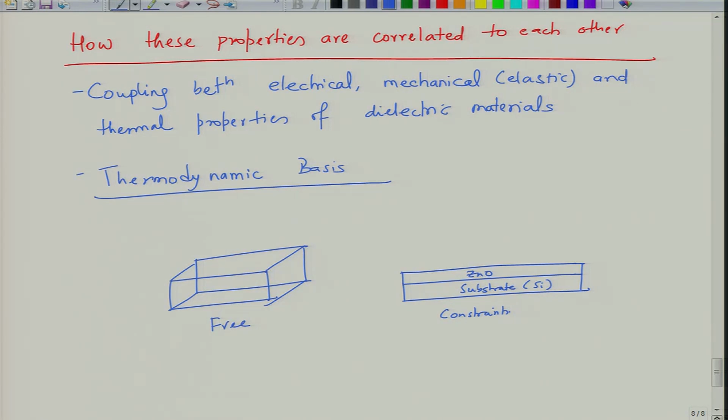So it is important to understand the effect of various variables on the calculation of these parameters, so that we exactly decouple various effects. For example, whether the piezoelectric strain is because of stress only, or does it also have a contribution from substrate-induced strain, or from differences in coefficient of thermal expansion between film and substrate, and so on and so forth.